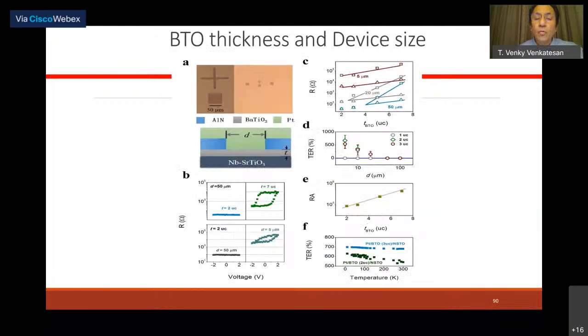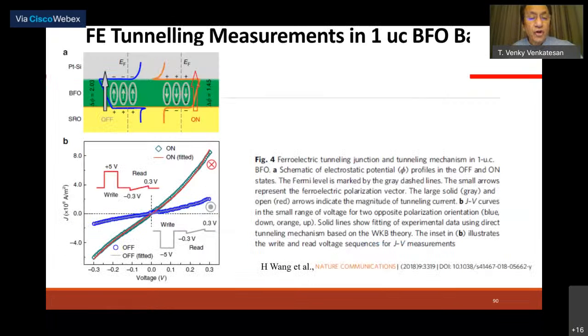Okay. But what is interesting is we've studied, for example, the number of unit cells of ferroelectric, and what happens to the RA product. And what we find is that the tunnel junction persists all the way down to 2 unit cells in this case of barium titanate. And in fact, here is an example of a 1 unit cell, in this case, bismuth ferrite.